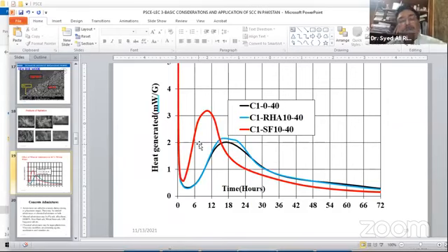So similar to silica fume, I think all should be doing the same, except that fly ash gives its pozzolanic activity after 14 days. I mean, after 14 days or 28 days, it gives you very high strength compared with the initial 7 to 14 days. But silica fume, right from the very beginning, starts giving you very high strength. The only precaution is that you must know the temperature of the resulting concrete which you make. And in the lab you can test, in the field you can test, and then you can decide the time of placement. You can place at night.